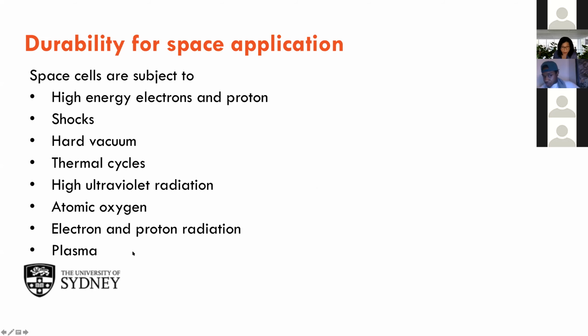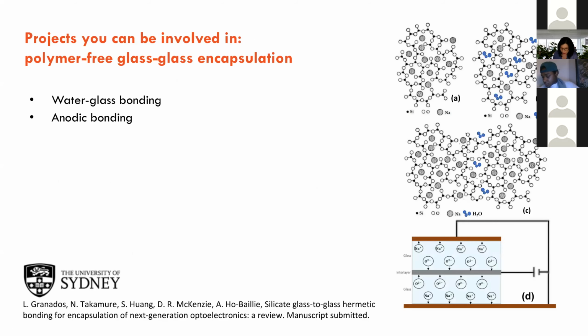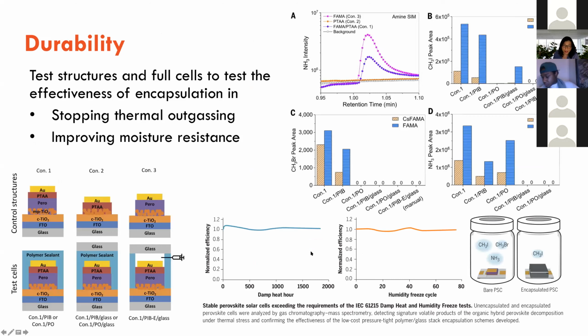And thermal cycles, we know it worked really well. I forgot to mention that. So here, what we did was, apart from looking at the decomposition products that are coming out, we actually torture the cells under damp heat and humidity freeze. So damp heat is 85 degrees Celsius and 85% relative humidity.